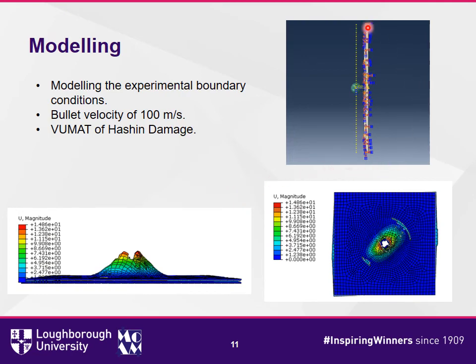The experimental boundary conditions were modeled in Abaqus software using finite element analysis. The steel bullet was given an impact velocity of 100 meters per second, which is around 15.5 joule of energy. Hashin damage failure criterion was used for the analysis. The result shows a ductile failure at the back of the plate, indicating delamination failure criterion must also be implemented in the model to match the experimental results.